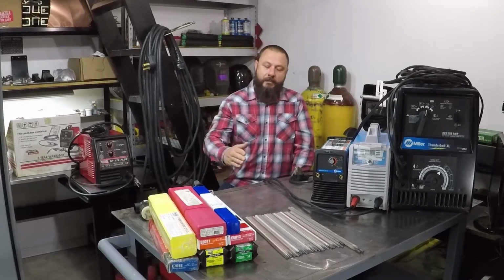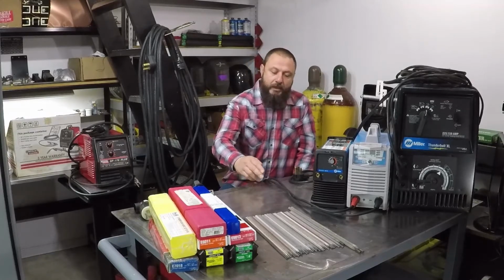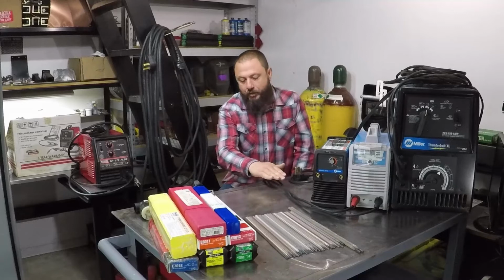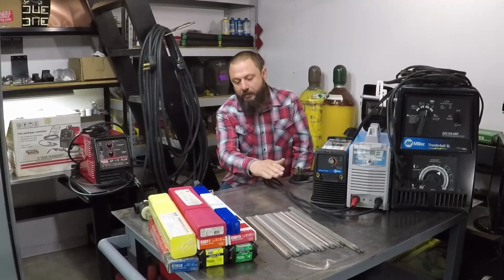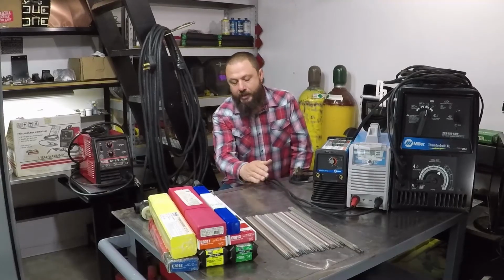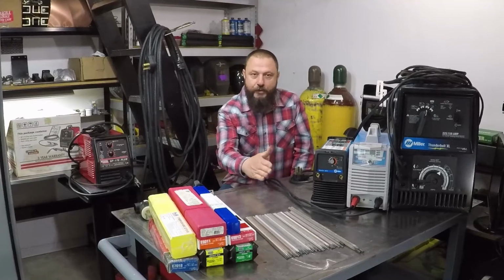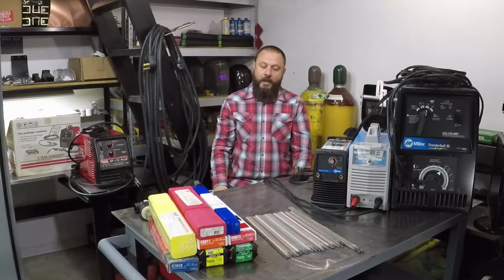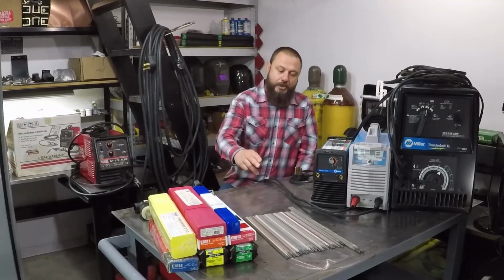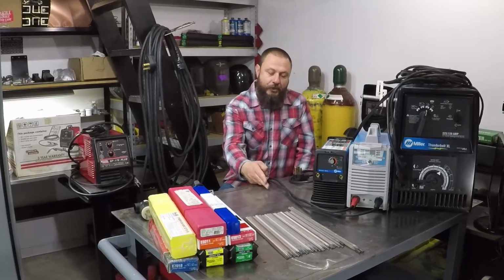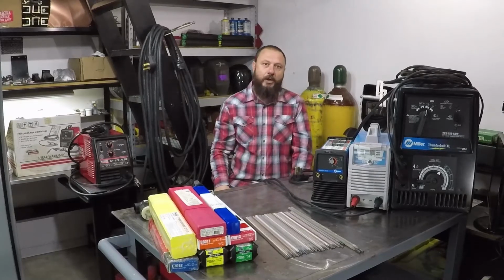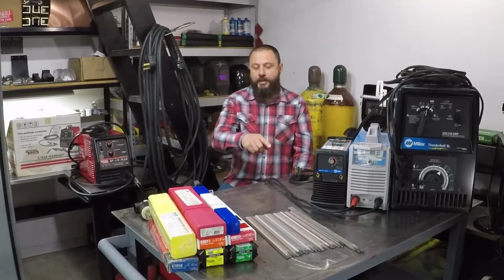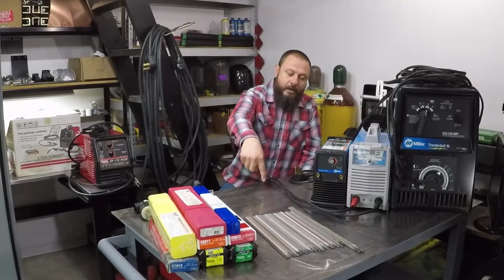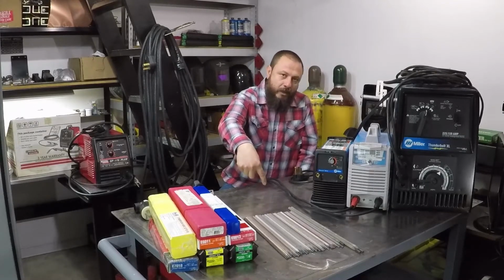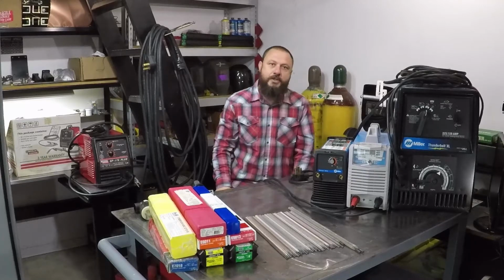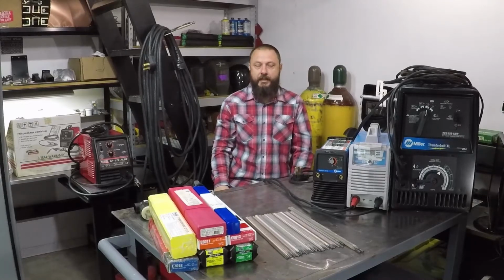Overlap. Sometimes after you finish your welding bead and you clean it, you discover that the weld material is laying on top of the metal. It didn't fuse to it. This could happen because your rod angle is set wrong or the current is set too low. So you could play with these two. Try to raise the rod angle more, or try to adjust your welder to a higher current setting.